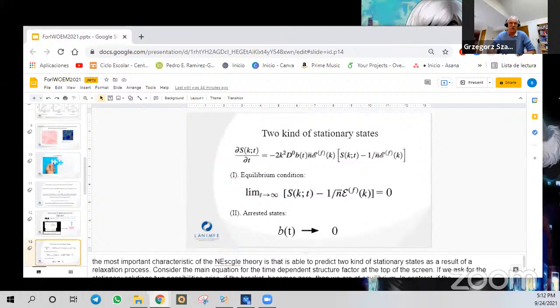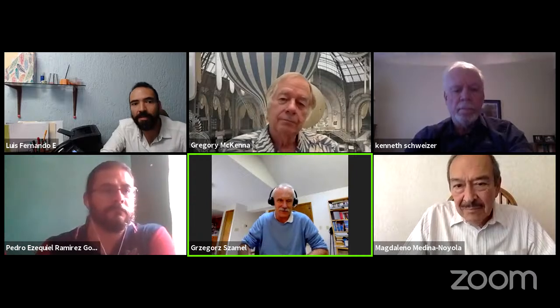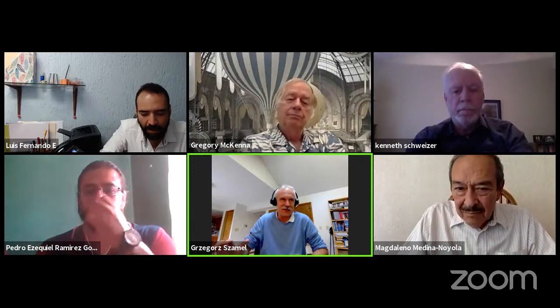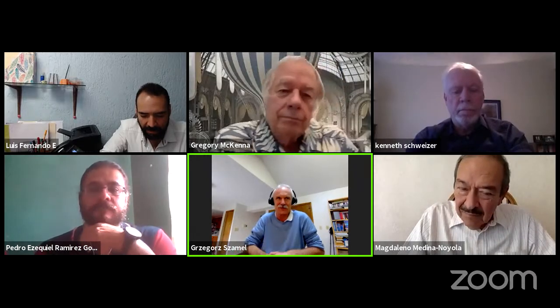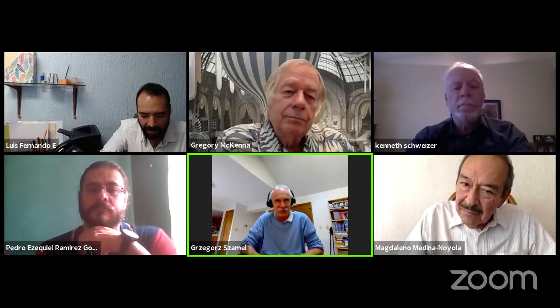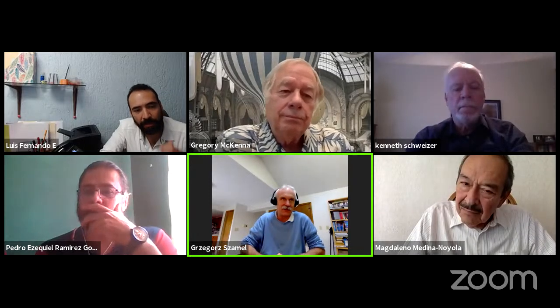I mean, I have two comments. One is that in Ken's theory, TG has to be emphasized. He said it many times, but I think it has to be emphasized very strongly. TG is an arbitrary number that is defined by requiring that relaxation time is 100 seconds. Physically nothing happens at TG. I mean, there is no transition, no nothing. So in my opinion, he can use his theory both below and above TG, and he would predict equilibrium behavior both below and above TG.